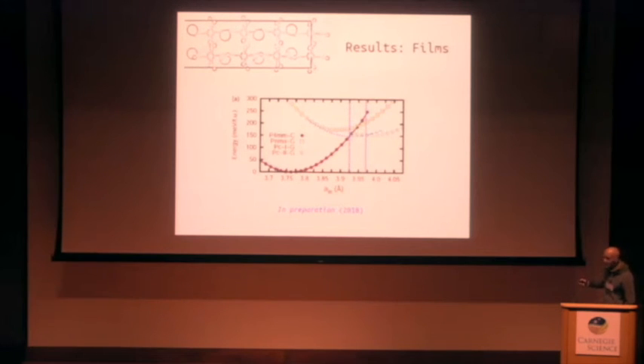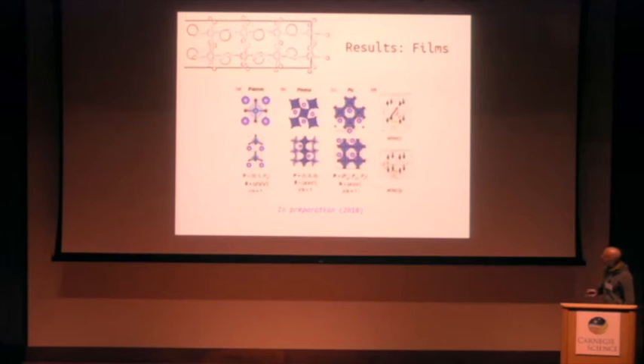So when you go down to tensile strains, that energy difference can really be tuned, right? You see that at some point the supertetragonal phase is not energetically favorable anymore, even at zero temperature. The thing is that in thin films, we have found that another phase comes into play, which is a monoclinic phase. Basically there are two, but let's just say one, which has some polarization that is not out of plane or in plane, so it has some direction, right? And it also has this pattern of oxygen octahedra.